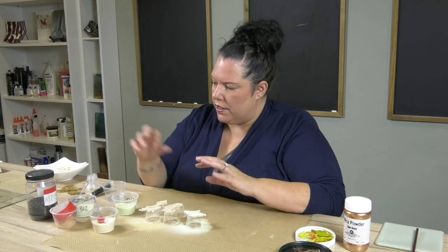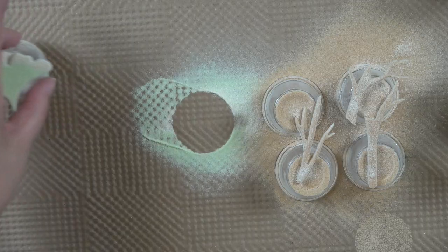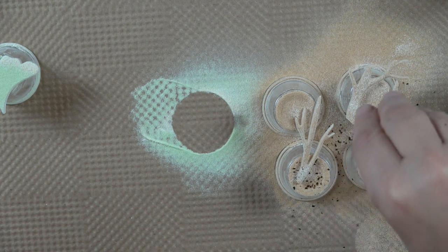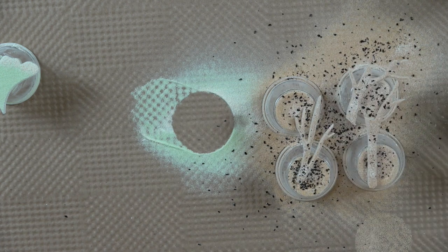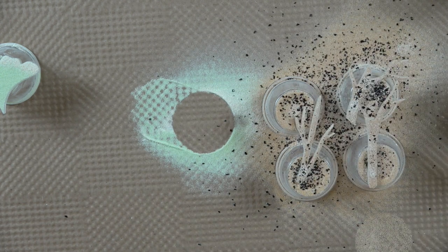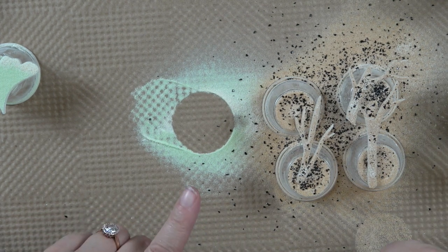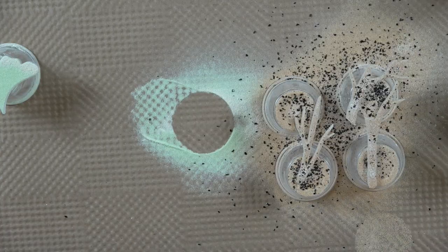So what I'm going to do is I'm going to take this fine frit, black fine frit, fine guys, fine. We're only going to 1300 for 10 minutes. I'm going to sprinkle it on the branches, okay? Give it a little sprinkle. All right. That's it, to make it a little more realistic. 1300, 10 minutes. Let's go ahead and fire these, and let's see how they come out.